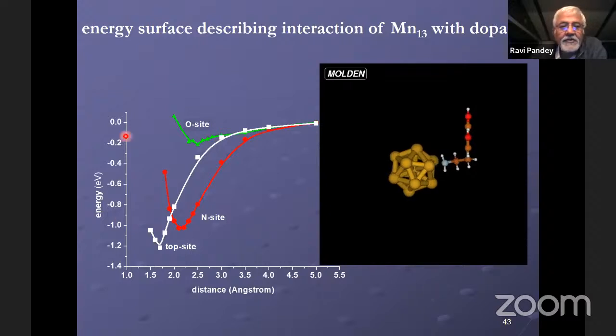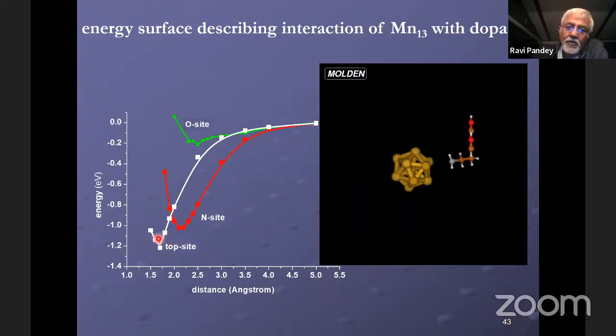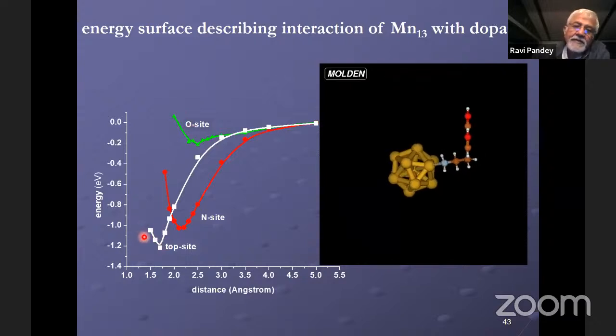And what we have is called the energy versus distance curve, the energy surface. And you can see here at the top site, it starts from way far away. There's no interaction. Then the energy goes down. That's a sort of ground state. And as we go closer to each other, the so-called Pauli repulsion takes over and energy rises. So from these three curves, you can see the top site has a lower energy compared to the N site and the O site. That means indeed this Mn13 nanoparticle prefers to bind dopamine at the top site. That solution comes out.